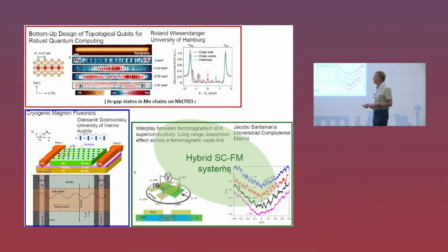And really, amazingly, if they then apply a current to the superconducting layer and the vortices start to move, they move at very, very large velocity. And this gives rise to the generation of so-called exchange spin waves in a ferromagnet. So these are very unusual kinds of spin waves, which have a very short wavelength. And it was shown that they don't form, as usually happens in a ferromagnet, standing waves, which don't transfer any energy. But there was a monodirectional propagation of these exchange spin waves, which can then transfer energy.